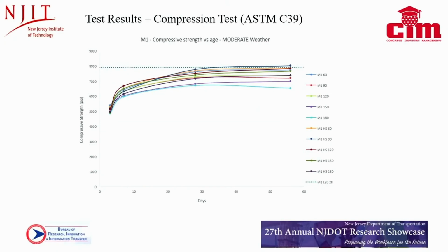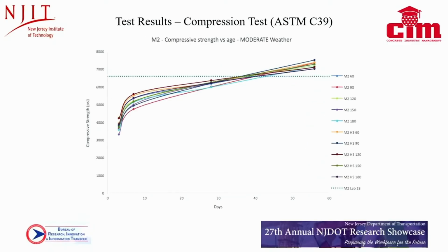I'm going to be going through this a little fast. Okay, so we have compressive strengths again. As you can see, the target was 6,000. We were able to meet that. If you look at, well, let's look at the 30-day line on the graph, and you'll see that we were definitely hitting our target beyond the 28 days with the concrete. Same for moderate weather. We hit our 6,000 psi target.